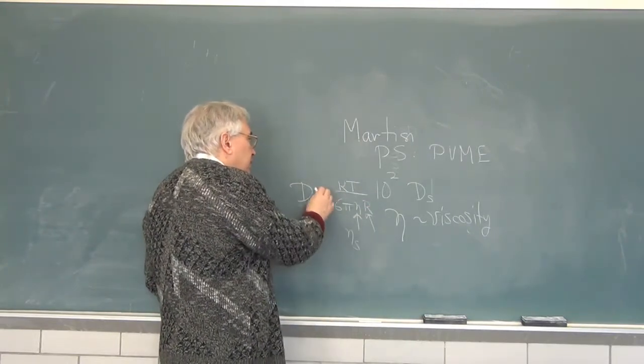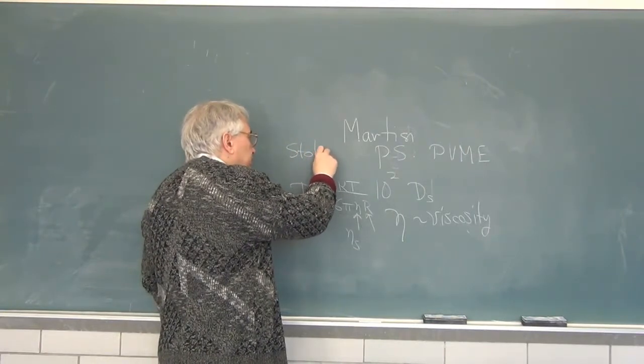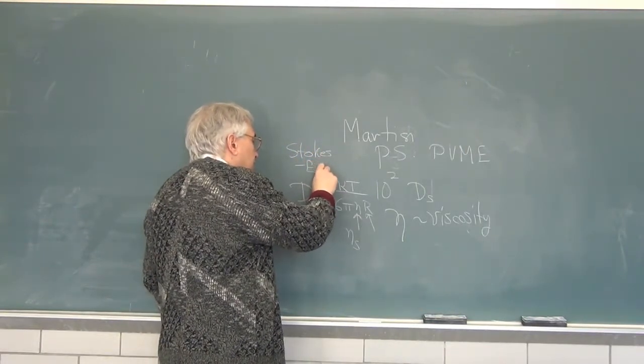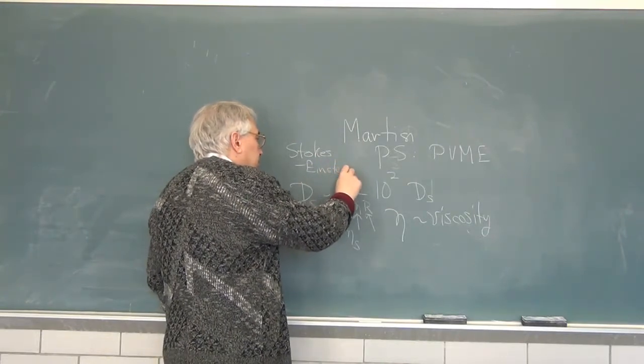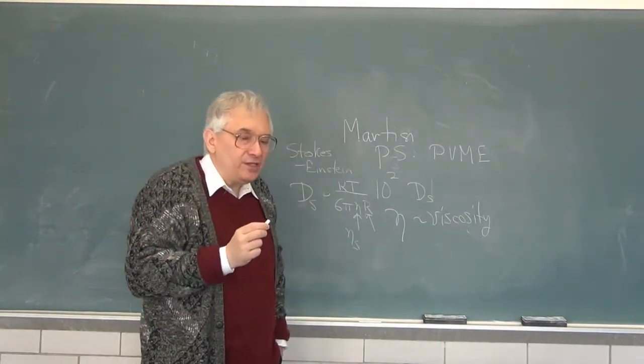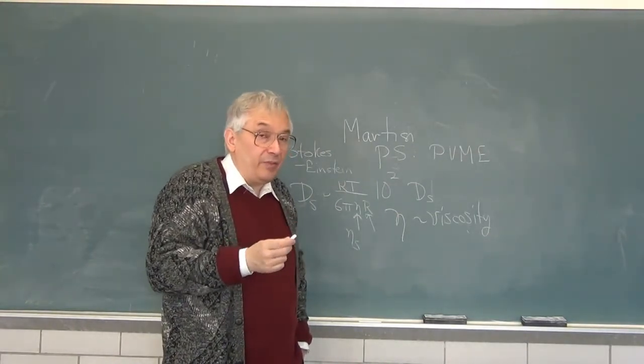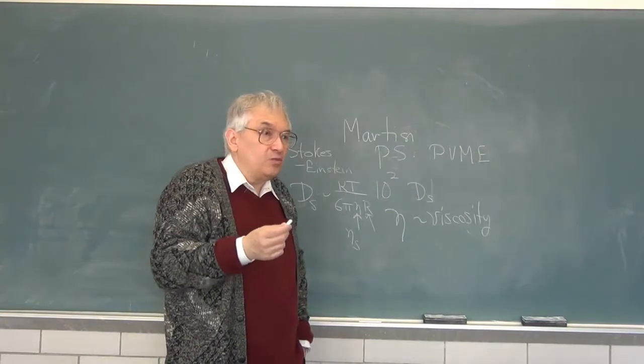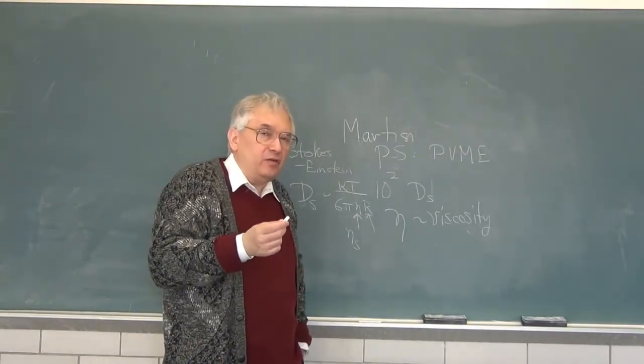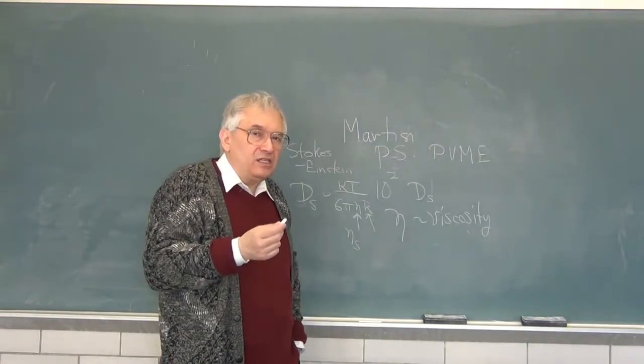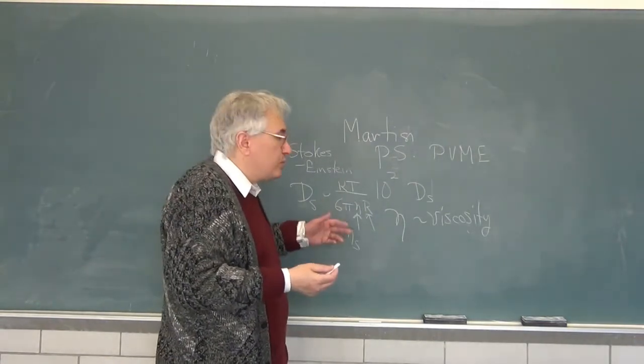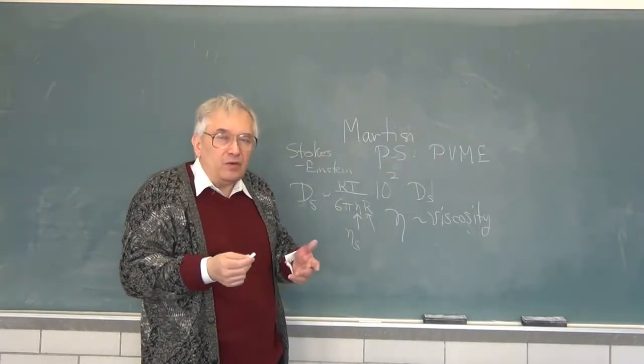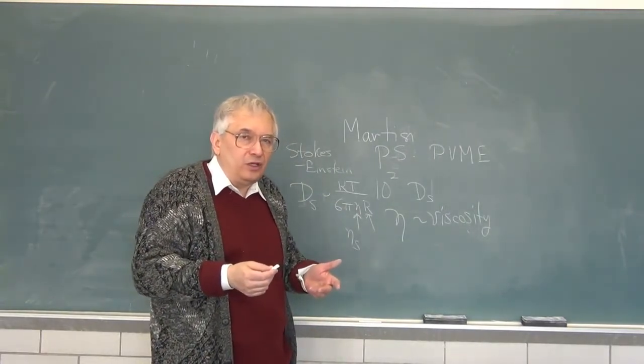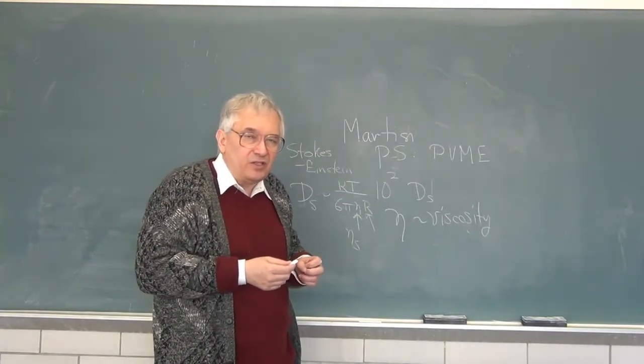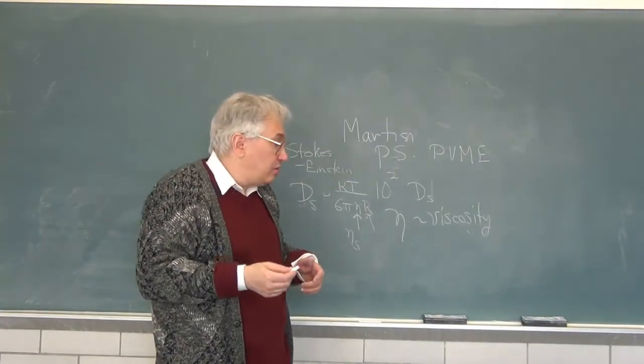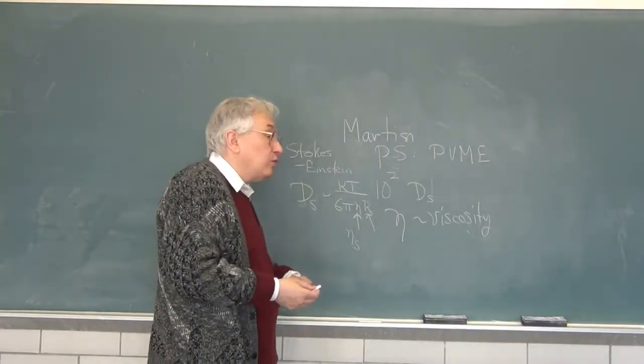R is the sphere radius. This is known as the Stokes-Einstein equation. The Stokes-Einstein equation, derived by Einstein a century ago, corresponds to an estimate of what the diffusion coefficient of a sphere should be in a simple liquid. It works all right for mesoscopic spheres. As we noted, if you go to ions or small molecules and you run up the viscosity above a few centipoise, Stokes-Einstein doesn't work right because the diffusion coefficient is not proportional to 1 over eta anymore.